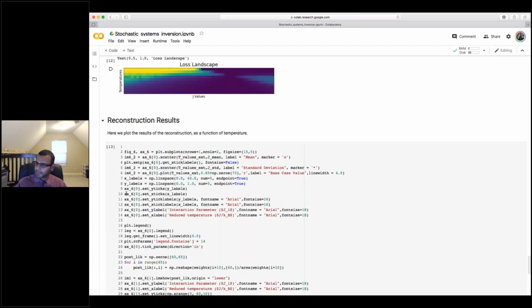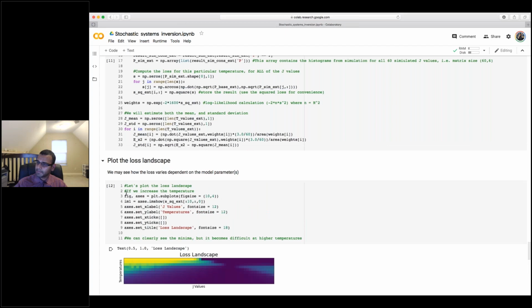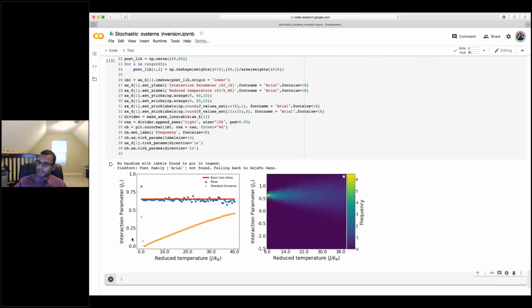The results shown here. This is the interaction parameter. So in our experimental case, we know the ground truth because we simulated it, and the ground truth features as far as this interaction parameter is concerned. So we took an image, we looked at the different configurations that it had, and then we tried to find the interaction parameter that best matched those configurations using an optimization technique, and we got this particular value, and we got a standard deviation as well.